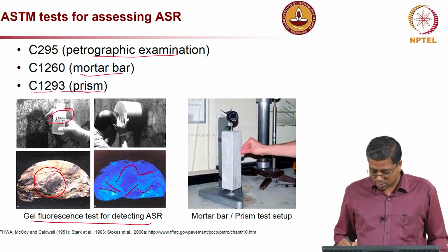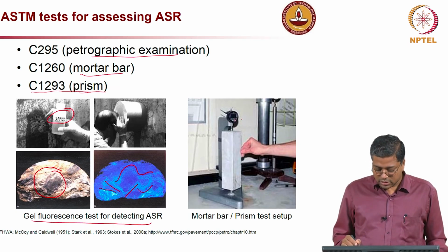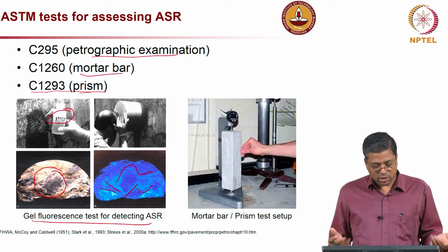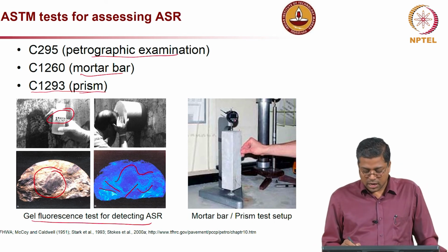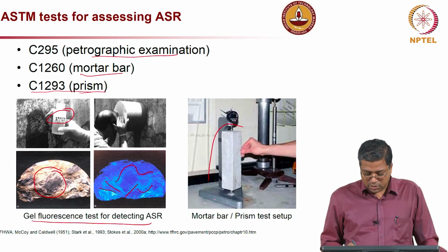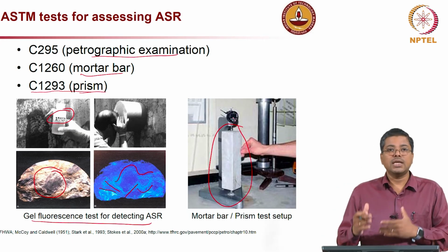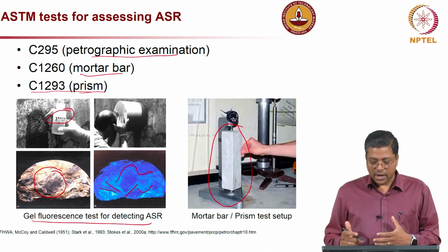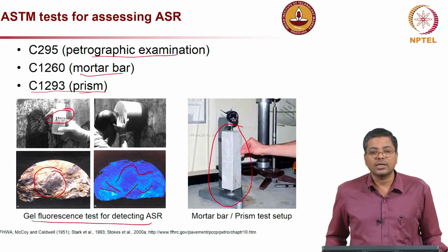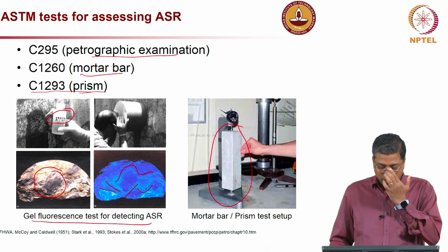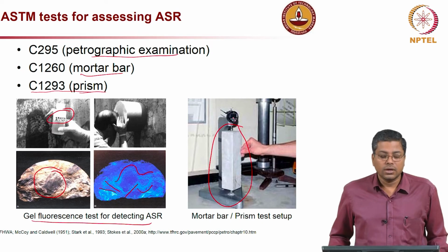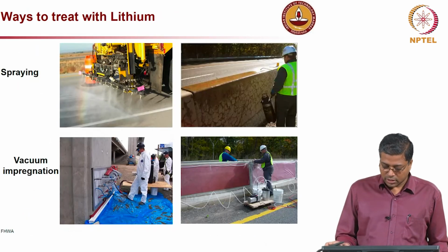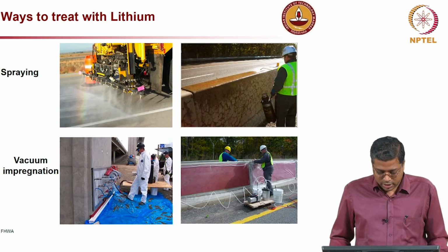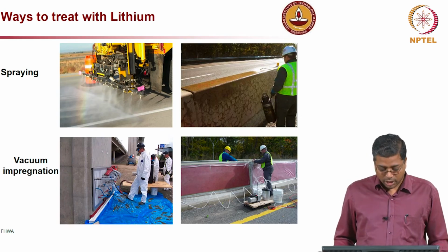So, the picture on the bottom right side is just to show you how both these mortar bar or prism tests are done. Basically, a prism is made, and then we look at the change in the length. If it is expanding, there will be an increase in the length of the specimen, and that will tell you how severe ASR type reactions can happen.